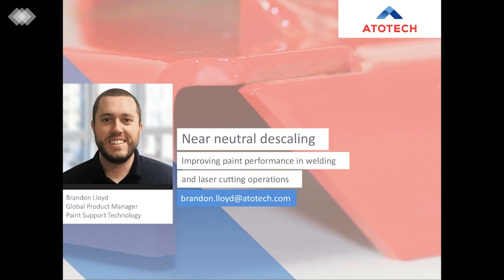The answer to this is really yes and no. The silica inclusions will be embedded at varying depths in the weld. So as the descalers remove the oxide scale, they will also remove some of the loosely bound silica as well, as we have seen in some of the SEM results from the slides earlier. For those inclusions that are not removed, the integration of surfactants in the Uniprep AC products formula offers improved organic soil removal, especially for those areas at the weld and around the silica inclusions, allowing for better bonding of the conversion coating and paint, which is what's helping in improving the overall paint coverage. And as a result of that, the corrosion protection for the part as well.